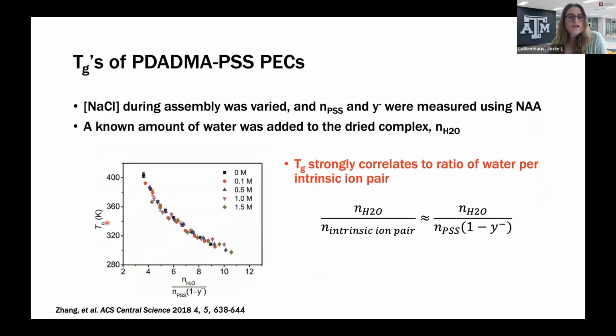So what we did was we measured the glass transition for these PDADMA PSS PECs that have been assembled in different salt concentrations. So they're going to have different extensive ion pairing. We used the method before to quantify the number of intrinsic ion pairs. We also added varying amounts of water to move that glass transition around. And we discovered that the glass transition temperatures all collapse onto a single curve when we plot it against this ratio of water to intrinsic ion pairing. So this gives a first clue that the glass transition is mediated by some kind of mechanism of water at the intrinsic ion pair. Okay.